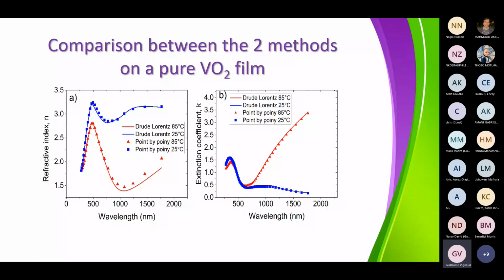Then here we can compare the refractive index and the extinction coefficient K obtained from the two methods on a pure VO2 film. We can see here there is not a big difference. One may think that the two methods are very similar, and this is true for this case. But we will see that for the tungsten-doped VO2, this is completely different, and there will be a strong difference.